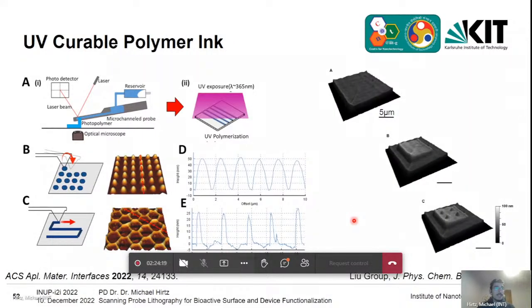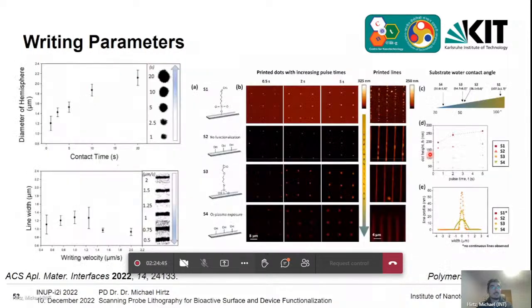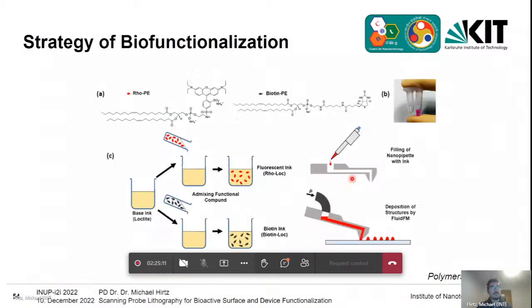As I talked about the lipids already, one other application is to use it for polymer inks. This is particularly interesting for us, and it is really ongoing work in our group: we use UV curable polymer inks in a layer by layer fashion to make really 3D printing possible, so micro 3D printing. Again, here we have different writing parameters, and the writing parameters were also applied for different surface features, like different surface energies. Again, writing velocity, contact time, and in this case you can see the height of the structures is pretty different for the different surfaces, so the surface influences this quite a lot.